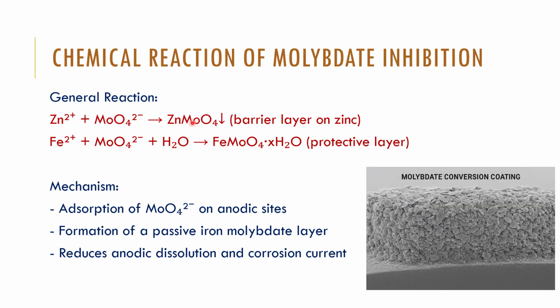What is the mechanism? This molybdate ion gets adsorbed on the surface, which is the anodic site. Then it forms the passive layer, forming the molybdate layer with the iron, with the zinc, all those things. Then reduces anodic dissolution and corrosion current as the process goes on. Initially, dissolution will be high. As the secondary layers start forming on, dissolution is almost stopped. So it reduces the corrosion process. So this way, this reaction takes place. This side you can see the molybdate conversion coating surface.